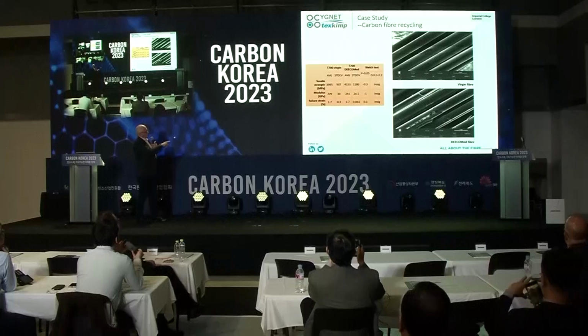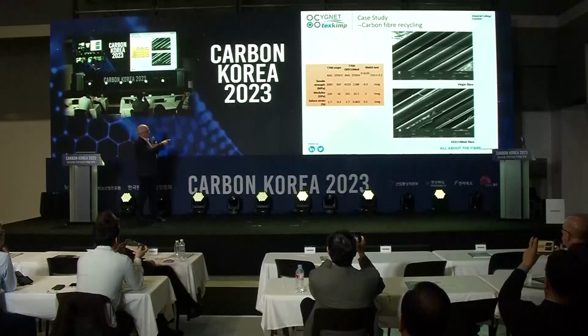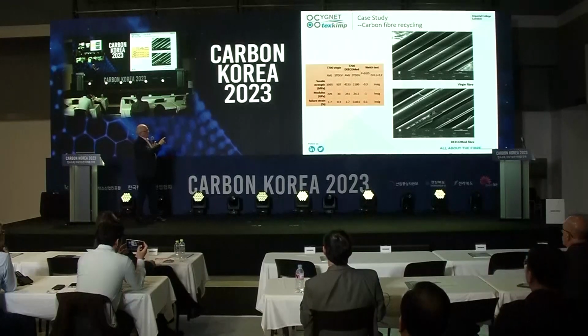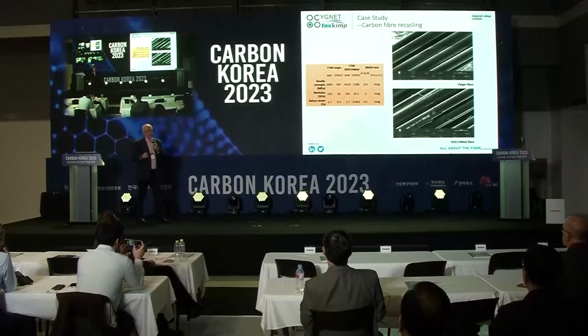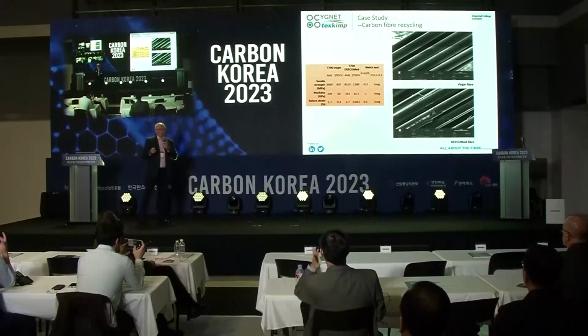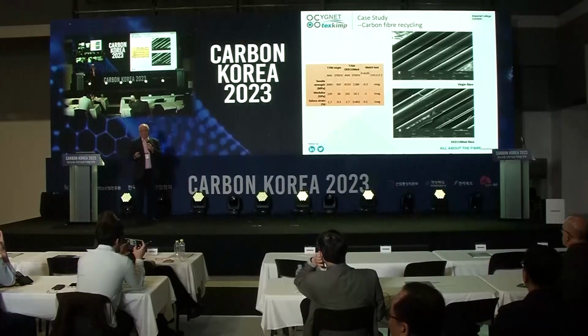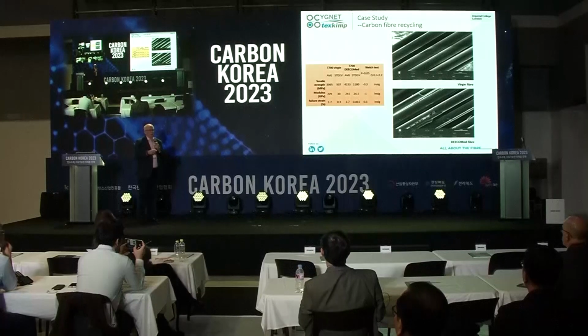You can see there's still some residual resin on there. We're not entirely sure what that is. That could be size. And of course, size is of great interest as far as recycled material is concerned, because commonly the size is removed completely. But what we found is that we can tailor this to leave elements of the material on there, depending on what the end use is going to be.